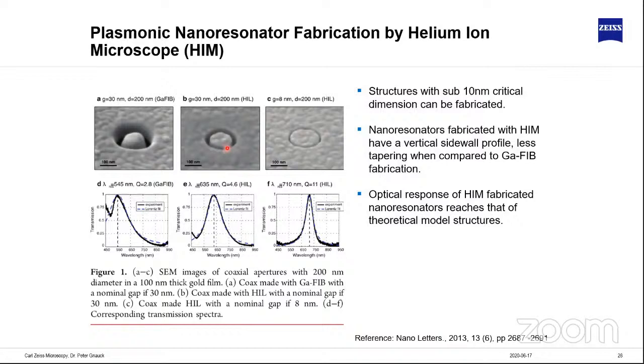And what we can do then is take that further and say, okay, we want to keep the 200 nanometers, but we only want a gap of 8 nanometers, and we can still do that with excellent precision. And if we do measurements on that resonator, we see we're exactly where we want to be, and we can really do physics with that, and we do not generate artifacts like with these broad ion beams in a gallium FIB.